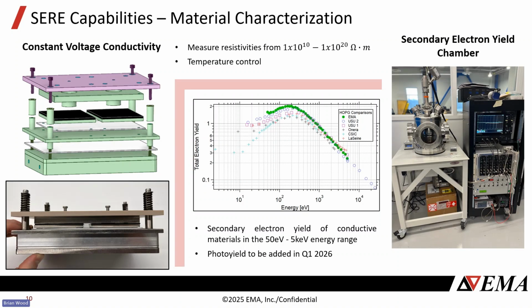For those of you who aren't familiar, basically you load a sample into this chamber. It uses a hemispherical grid retarding field analyzer, which is basically just a dome that's sitting over the sample. You pick an electron beam with a single energy, you shoot it at the sample, and you're measuring how much current is going into the sample and how much current is coming off of the sample. You can shoot electrons at a material, and either they could all go in there, or they could actually excite electrons in that material and give them enough energy to escape the material. And so you can actually charge something positively with an electron beam, and the secondary electron yield measurement tells you what that yield is for a given electron energy.